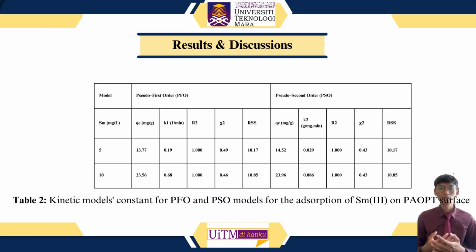Furthermore, the estimated Qe values of the second-order model are more closely aligned with the experimental values for all the starting samarium concentrations. Therefore, it may be stated that the pseudo second-order model is more appropriate for elucidating the adsorption kinetics.